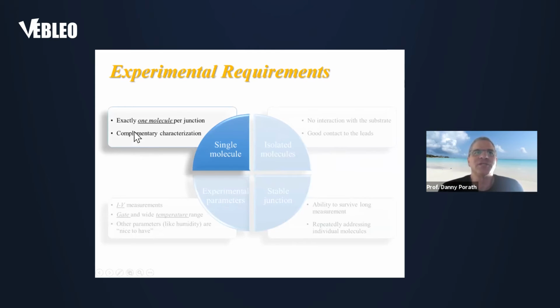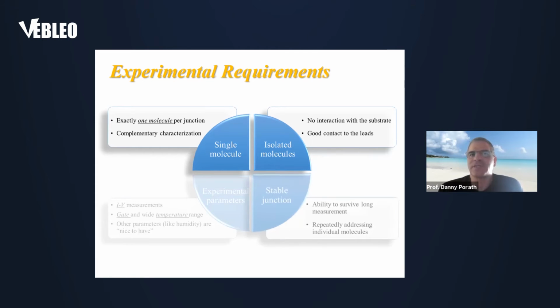So the first requirement would be to have exactly just one molecule in the junction. In addition, we want to have complementary characterizations. So another way, by AFM or by SEM or by another way, where we can see that the molecule is indeed there. In addition, we want an isolated molecule. So we want to avoid interaction with the surface that, as I explained, may decrease the current. And we want to have good contacts to the leads. And we want to have a stable junction.